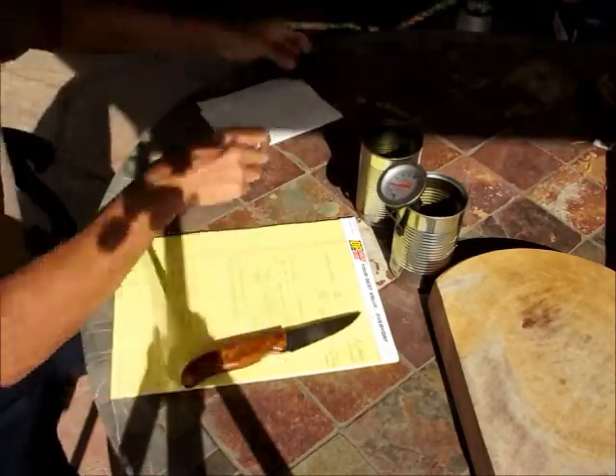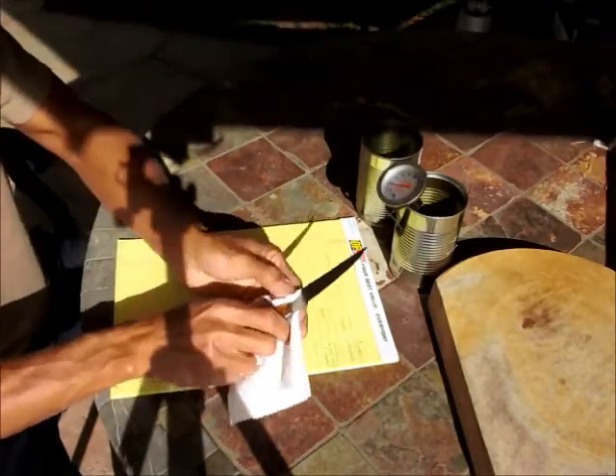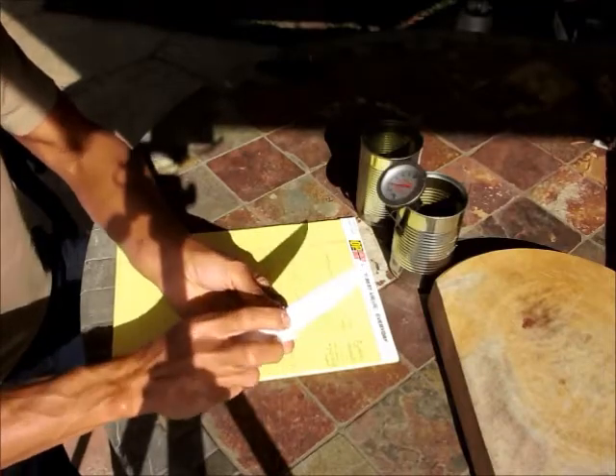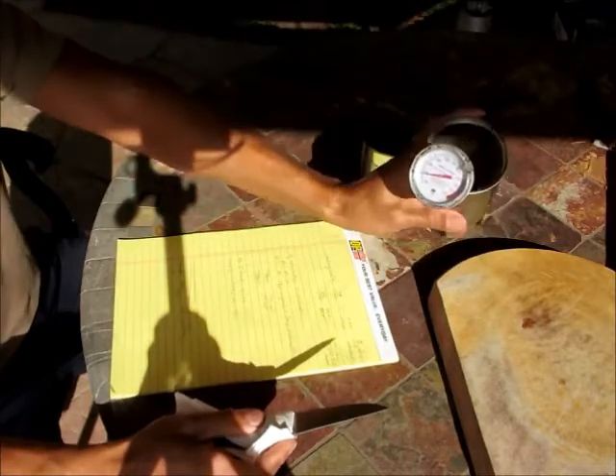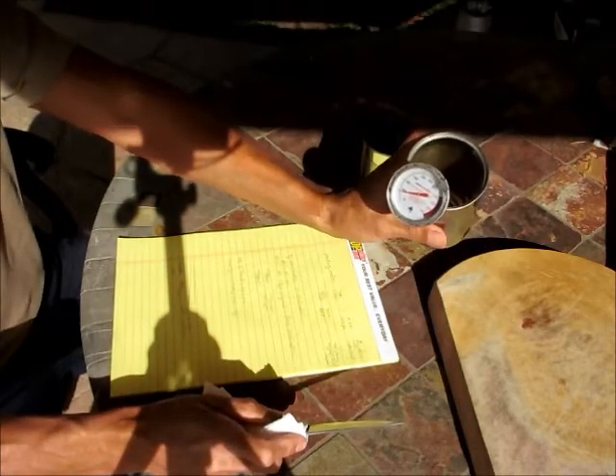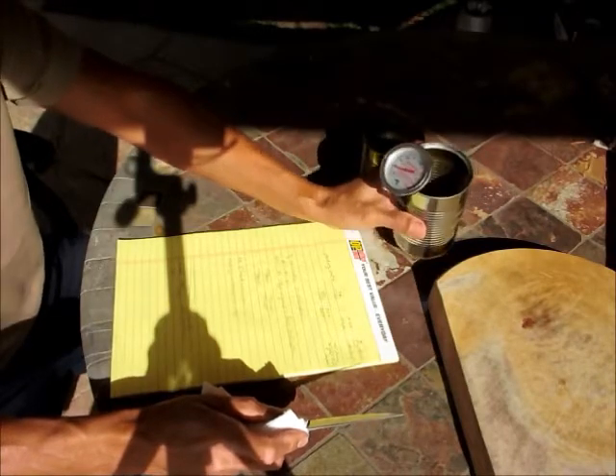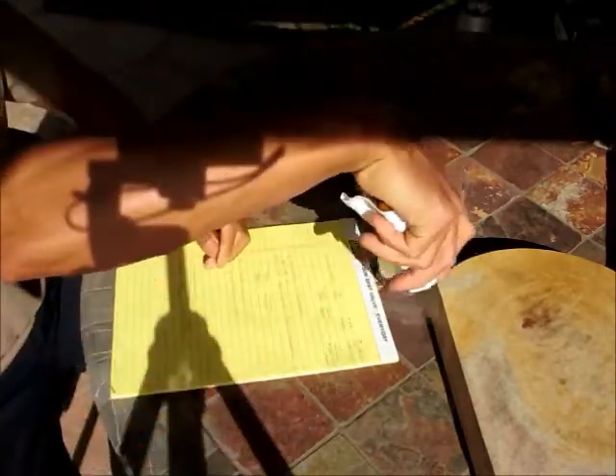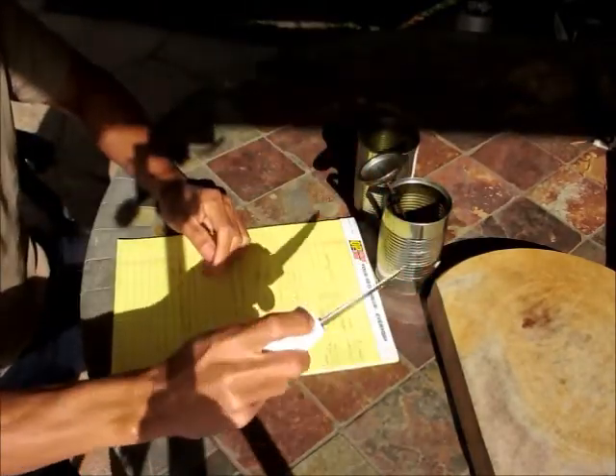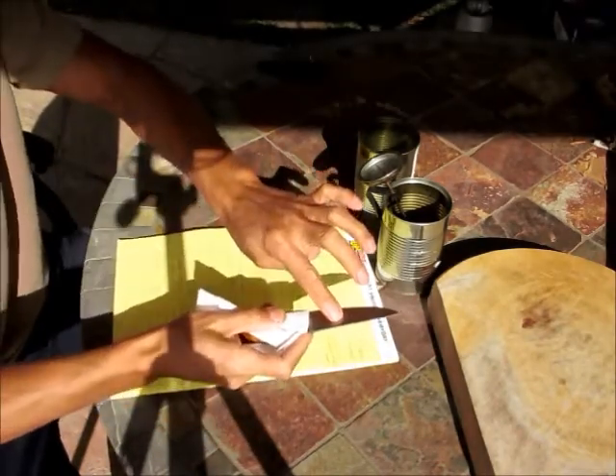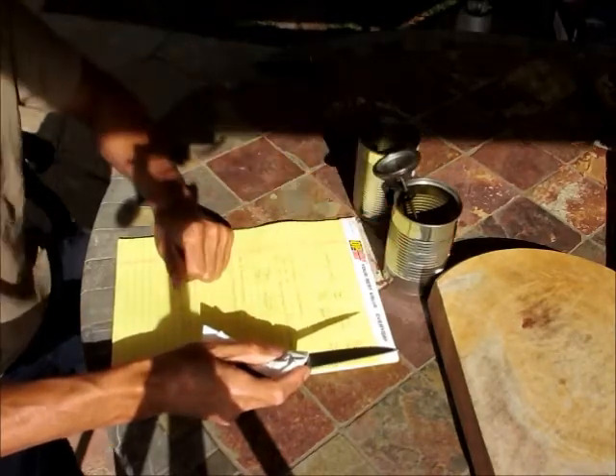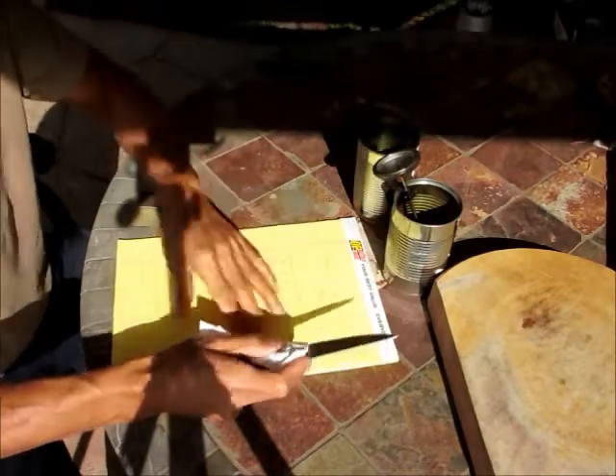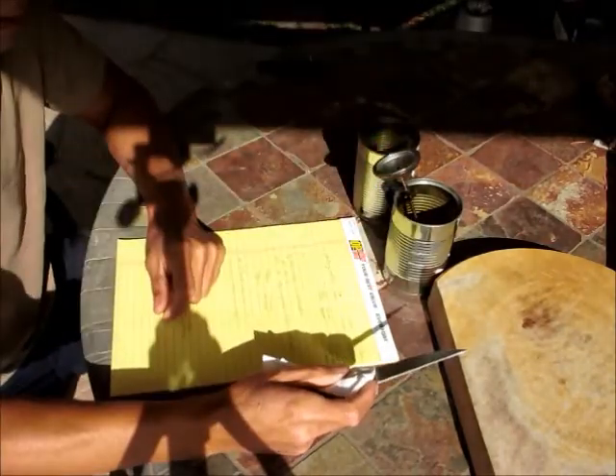Okay, say this is a container of ice water, and pretend that's so. Dip the thing in here to cool the handle, and get some wet paper towel. Grab around the edge, with wet paper towel. Heat up to the temperature. I would recommend about 190 Celsius, or 170 or 180. You heat up canola oil, dip the blade in there, move it around, and you can put your finger here to feel whether it's too hot on your finger or not. Watch the edge because it is thin. It heats up very fast, and in liquid it conducts right into the blade, heating up quickly to the temperature. After five to ten seconds, dip it into the ice water, then dry it, and then dip it in the oil again.